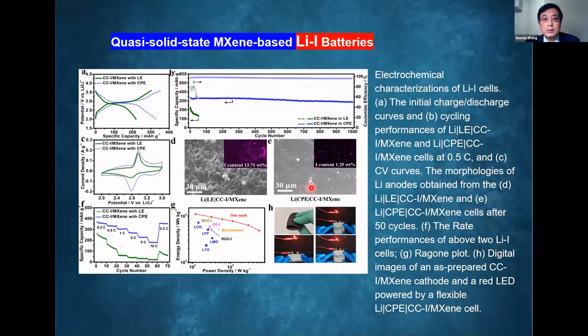And this is the electrochemical performance. You can see when we use MXene-wrapped carbon cloth as the cathode, we can achieve extremely good electrochemical performance up to 1,000 cycles. But if you don't use MXene wrapping, just using the bare carbon cloth, the electrochemical performance is very poor. The battery cells quickly failed on cycling.